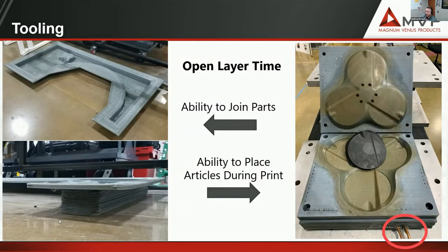So it was nice to see that we were able to get that 90-degree angle, and that's really due to the open layer time and how we could bond these materials together. That is a great benefit of being able to do that and actually lightweight that product. So we're taking out material and not building material all the way up that height to reach that flange and having a solid flange. The mold on the right is a mold that Oak Ridge decided to print.